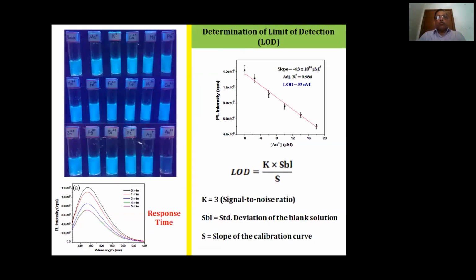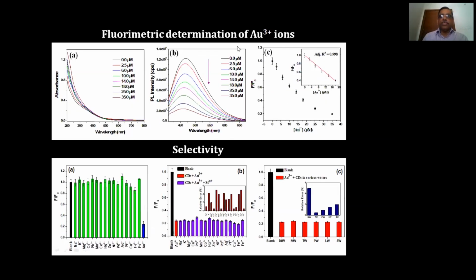And then when you go for the extension of sensing the metal ion - gold as a metal ion - we could see that again fluorescence quenching is happening, and we could selectively sense the gold ion in the presence of other metal ions. This is how selectivity is extensively brought in.